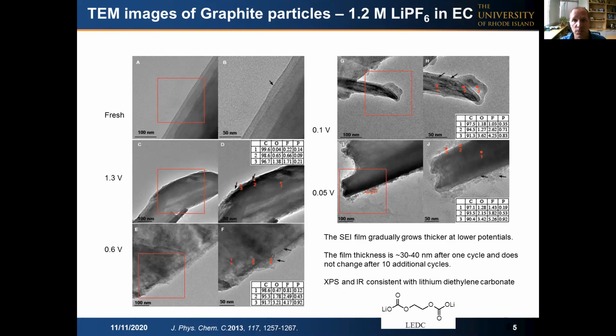One of the challenges with the electrolyte is when you have an electrolyte that has 3 or 4 different components, each of those components is going to contribute to the compounds that are present in the SEI. And if you simplify the number of components and you still get a functioning cycling battery, then what those components are, they do comprise a valid SEI. And in this case, many researchers have reported that EC is the central component, the most important component in SEI formation. And so that's why we use the simplified electrolyte of LiPF6 in EC.